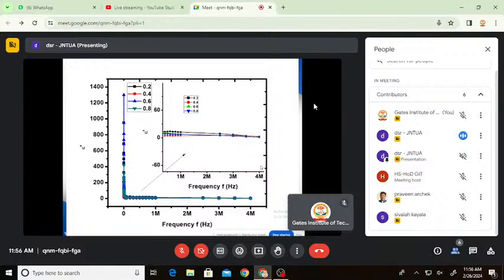So coming to the dielectric studies, from the plots, it is clear that epsilon dash and epsilon double dash values are found to be higher at smaller frequencies, whereas the values are small at high frequencies, which may be owing to the inhomogeneous dielectric structure. Consequently, the high epsilon double dash was owing to the contribution of grains at low frequencies. Besides that, grain boundaries may be accountable for the small value of dielectric constant at larger frequencies.